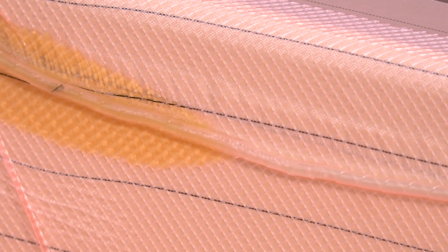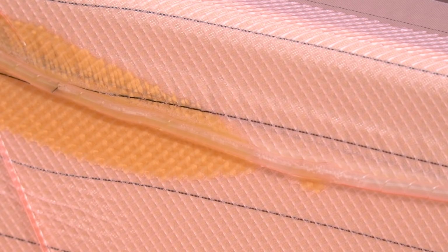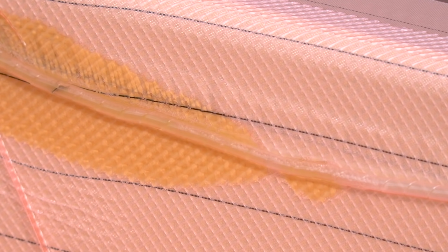Immediately, you will see the resin flow down the spiral and into the mesh and reinforcement. Don't worry if you see a few small bubbles rushing forward on the leading edge of the flow. This is normal, especially with resin that hasn't been degassed. It's simply the microscopic air bubbles in the resin expanding exponentially as they approach the near absolute vacuum in front of the flow.